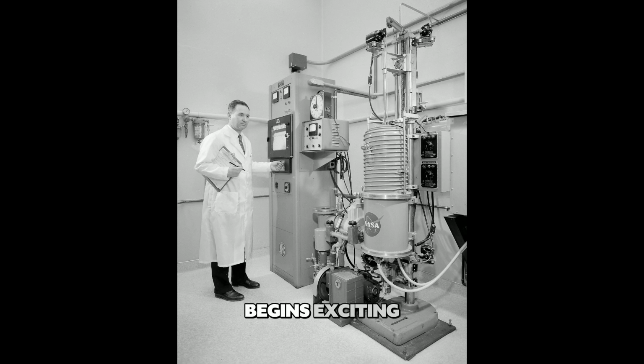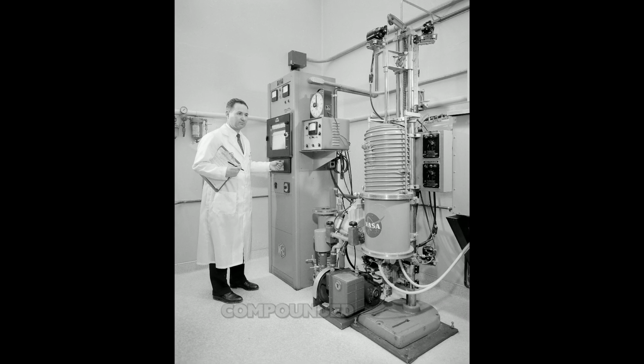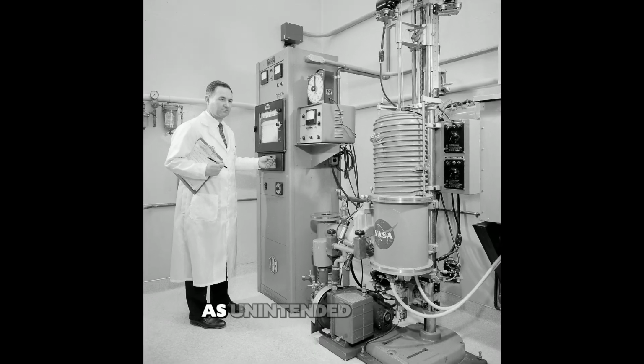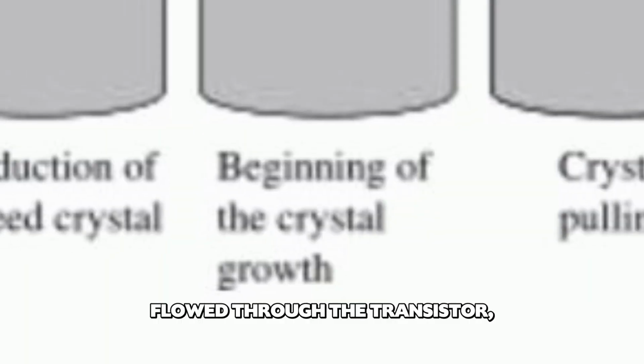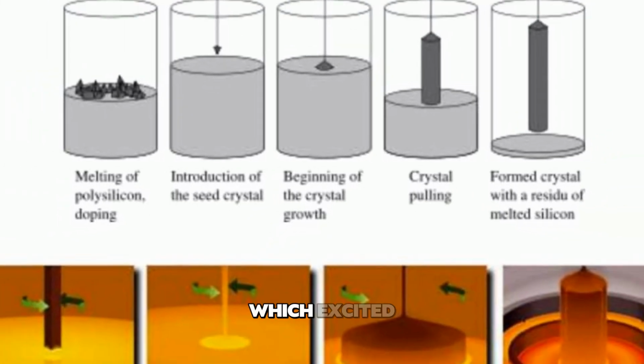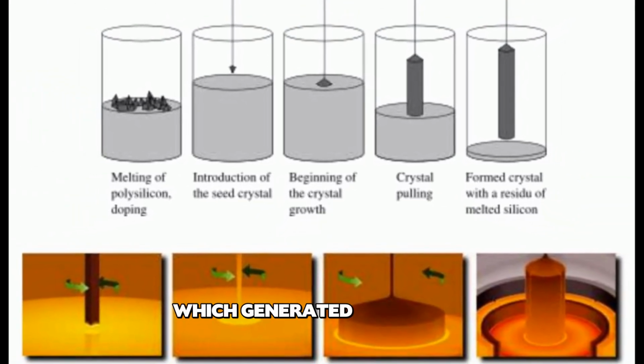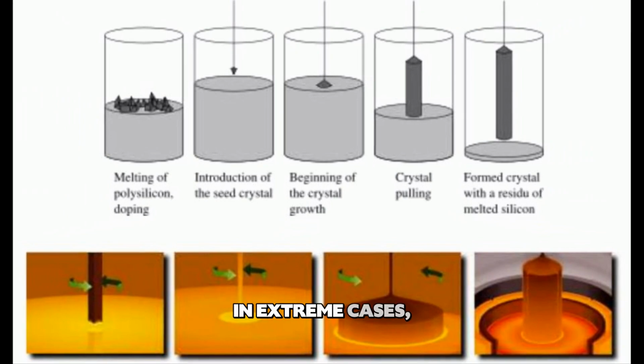thermal energy begins exciting electrons across that gap spontaneously. By 85 degrees Fahrenheit, enough electrons are jumping the gap that germanium starts conducting current, even without applied voltage, a phenomenon called thermal runaway. The problem compounded itself. As unintended current flowed through the transistor, it generated heat, which excited more electrons, which generated more heat. In extreme cases, germanium transistors would literally cook themselves into permanent failure.